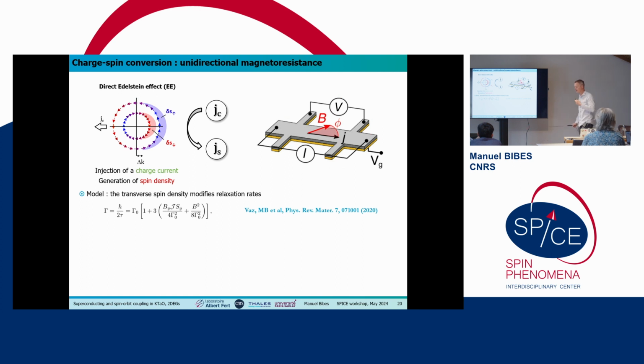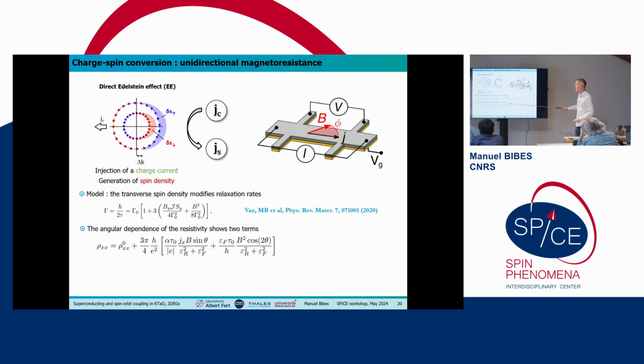Okay, so then we have another way to measure the Rashba coefficient using transport. For that, we take advantage of the Edelstein effect. If you remember, we apply a charge current, and this is going to generate a transverse magnetization. In this case, the presence of the transverse spin density is going to modify the scattering rates in the system. And at the end of the day, we end up with a longitudinal resistivity, which is going to comprise 2 terms. And this one is the most important.